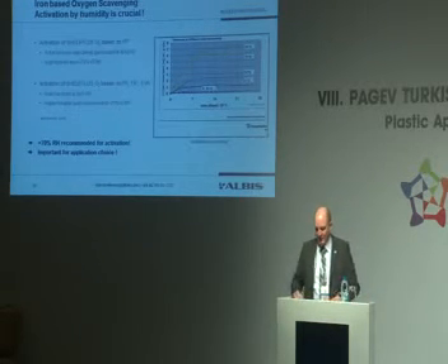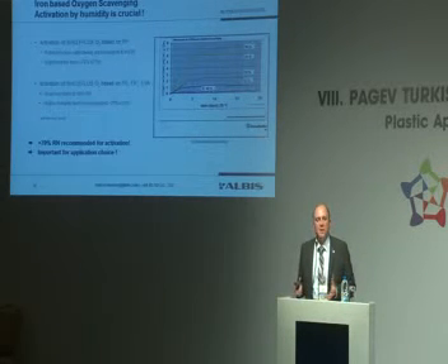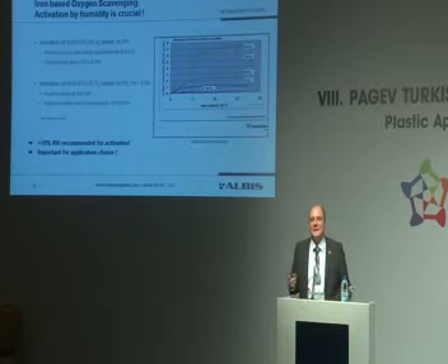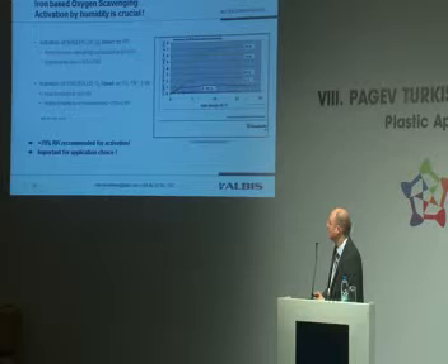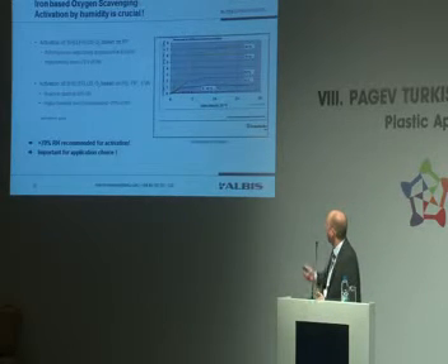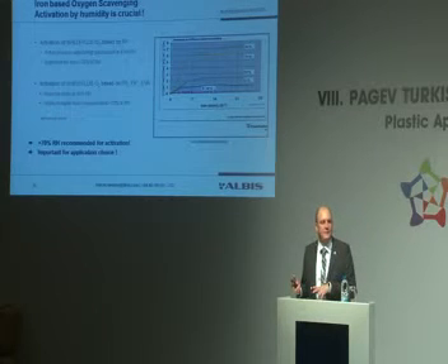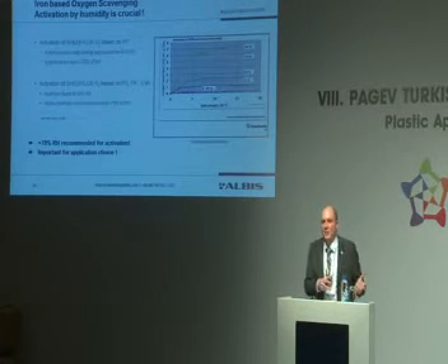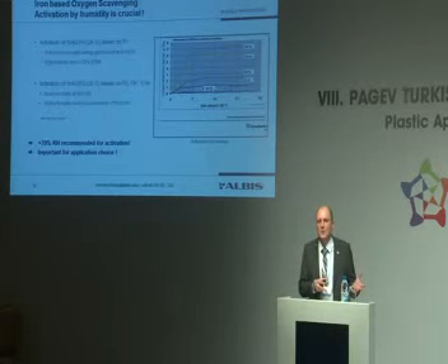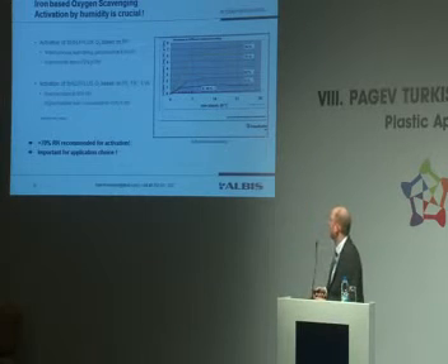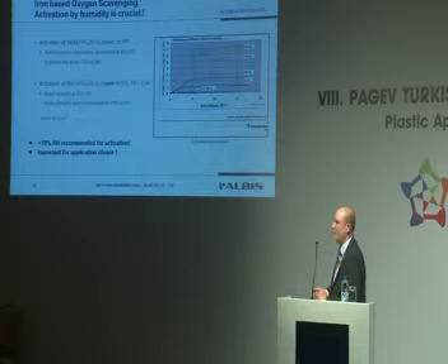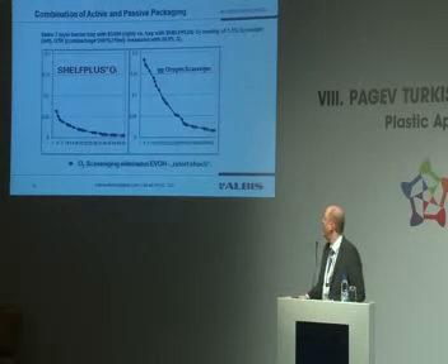Now, what many people are not considering, me standing up here in front saying humidity is important sounds easy, but if you have a real life application, sometimes it becomes not so easy anymore. So we have shown here some graphs of the absorption capacity of such an active oxygen scavenger at different humidity levels. And you see, if you work with 60%, 50, or even only 43% humidity, it would not activate. You don't get the oxygen absorption. So this is for some applications a benefit, for some applications a disadvantage. For example, paprika powder, dry things. You will not be able to scavenge the oxygen out of such a paprika packaging. So you really need to have products that carry enough humidity to work with iron-based oxygen scavengers.